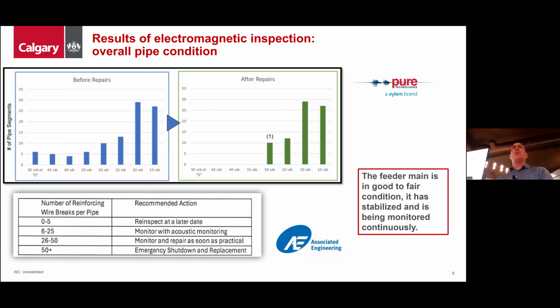And it can identify where there's a break in that wire and the continuity of the wire. So that's how it senses wire breaks. We've used the pipe robot, which is just a tracked vehicle that you would put in a dry pipe. And the pipe diver requires the pipe to be fully in service. So we're able to use a hot tap like you would in the oil and gas industry. You would hot tap on either end of the pipe that you want to inspect, insert the diver while it's in flow conditions, and you quite literally insert a net into the pipe at the other end, and you catch the diver. There's nothing too magical about that at all.